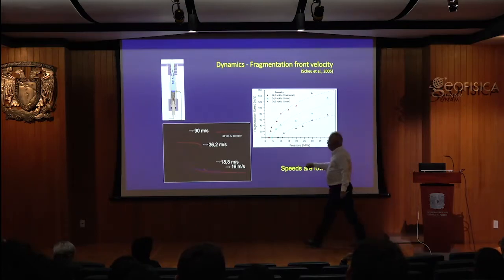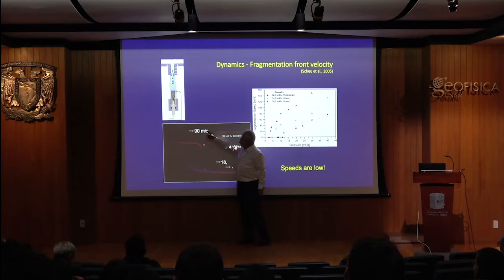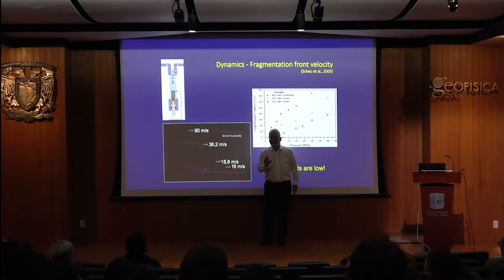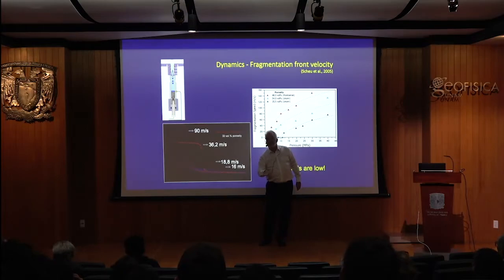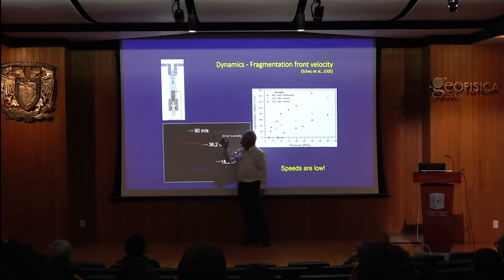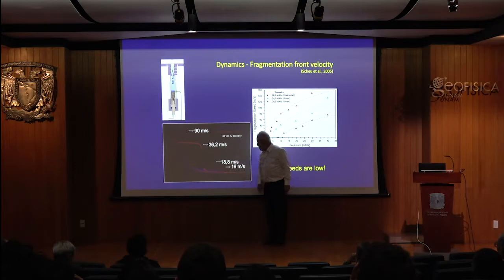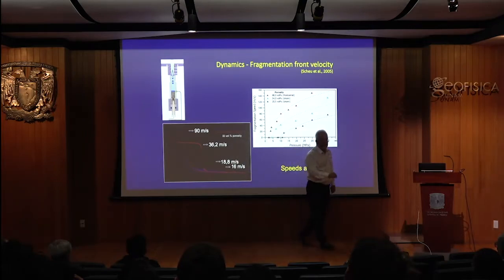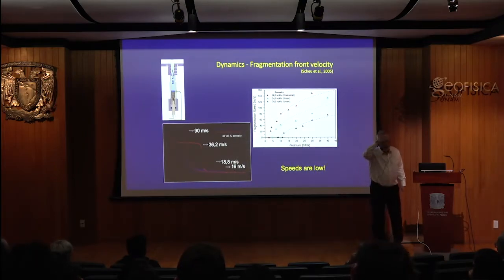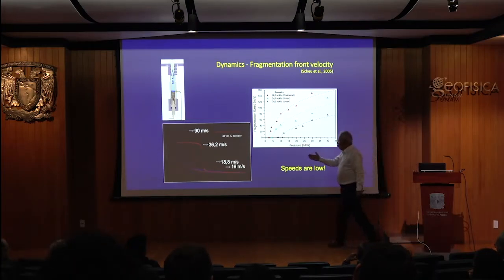Well, I use my hands. Look at the numbers. These are the results of dynamic pressure sensors. So I measure the pressure above the sample and I measure the pressure below the sample, on a microsecond time scale. And what I see is the decompression difference in time gives me effective speed, 90, 36, 18, 16 meters per second for the erosion of that fragmentation front. Think of it as an erosion or milling down into the magma, okay? These are not very fast.